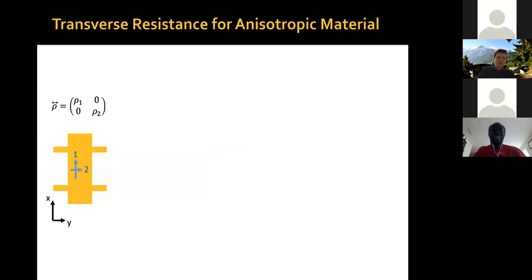So now, how is that possible that you measure the finite resistance? Well, let's imagine you have an anisotropic system, a system where the resistivity is a tensor, and you have different resistivity along direction 1 and along direction 2. Now, if you're doing a measurement in a Hall bar geometry, where the X and Y axes of your device are parallel to your anisotropy axes, the X component is the 1 axis, the Y axis is the 2 axis, then you measure indeed at zero magnetic field, even in the presence of this anisotropy, zero transverse resistance.